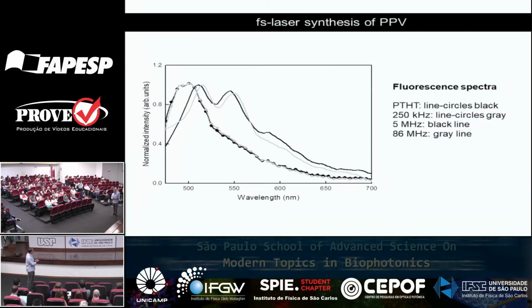So here are some results. So depending on the conditions you use, you might have or not the conversion from the precursor polymer to PPV. So if we use high repetition rate, here is where you get a better conversion, for instance, right? So the gray line here. So that's where you get the better conversion. So if you use in here, for instance, low repetition rate, so that's the gray circles there. You don't get the conversion.